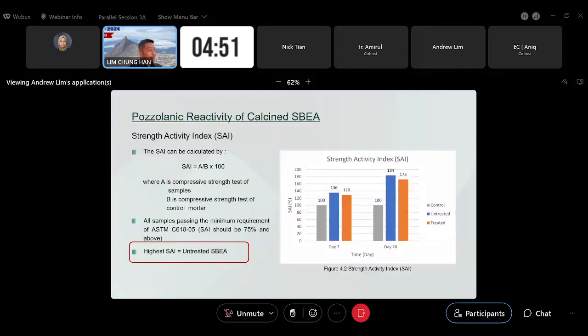The first test, strength activity index. You can ignore the text on the left-hand side; we just look at the graph here. The gray color is the control at 100%. You can see the untreated pozzolan achieved an improvement of 36%. It's gone up to 136, so that means it's an improvement of 36% over the control. Whereas the treated sample only improved by 29%. This is for 7-day strength, by the way. If you look at 28-day strength, you get even more improvement.